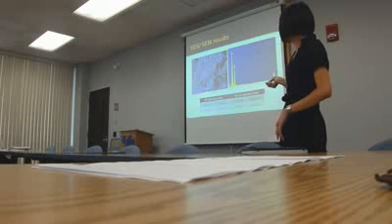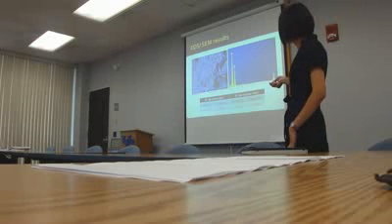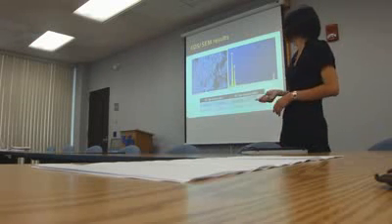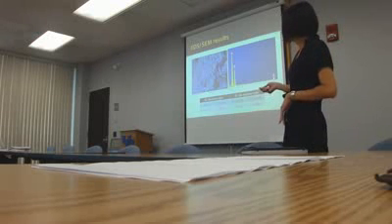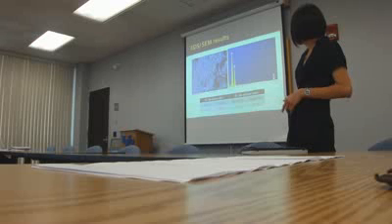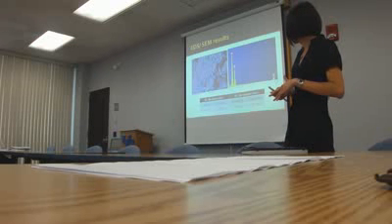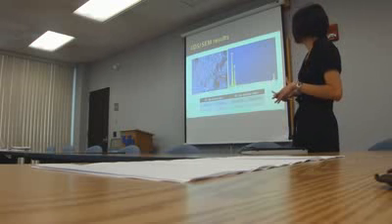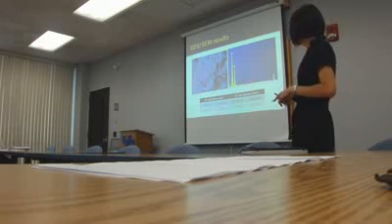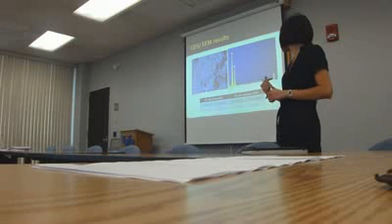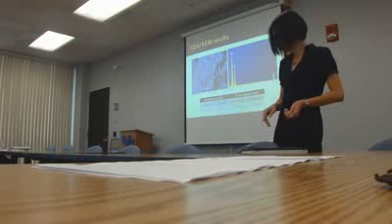So this is a sample of the silicon-germanium particles, and we pick a random particle in this area to do the EDS characterization. The graph shows that both germanium and silicon are present in that particular particle. Also, we can get the atomic fraction and weight fraction from the EDS characterization.